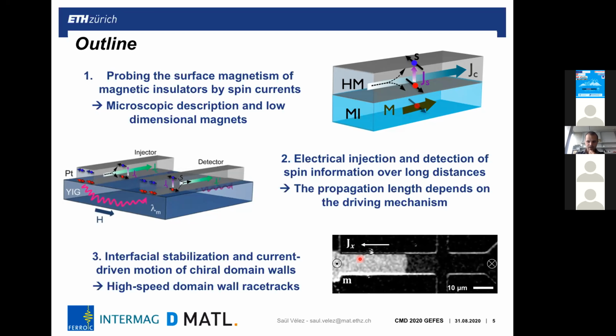And in the last part, I will show you that we can switch the magnetization locally in a magnetic insulator by having a platinum line on top of the magnetic insulator. And this same platinum line can also stabilize homochiral domain walls and drive them by charge currents.